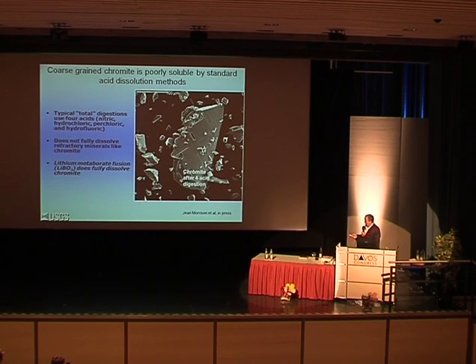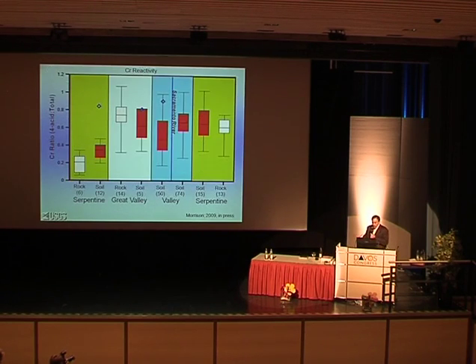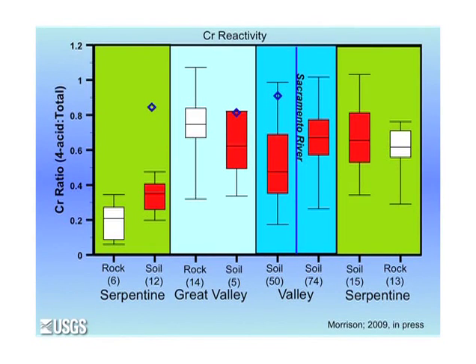This is a shot of a chromite grain after the four acid treatment. It's slightly etched, but not much. So we can use that as kind of a crude reactivity guide. So this is a box and whisker plot where the lower end of the box is 25th percentile, the top is 75th, the median, and the 5th and 95th percentile of the data. The data is arrayed from west to east across the study area.